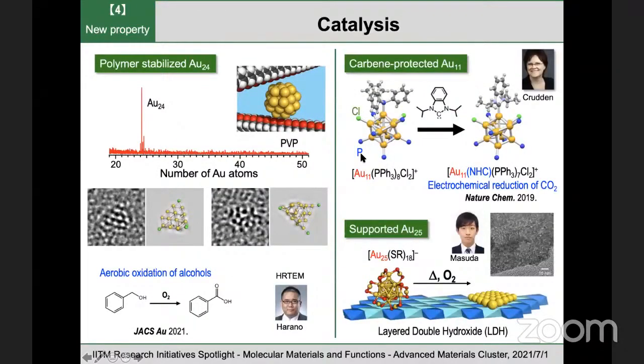So we are also interested in the catalysis of superatoms. And we recently successfully synthesized a new gold superatom, Au24, in PVP polymer matrix. High-resolution TEM images show that the structures are fluctuating all the time. And with the help of DFT theoretical calculations, we realized that all atoms are located on the surface of this superatom. And they show very high activity for aerobic oxidation of alcohols in water.